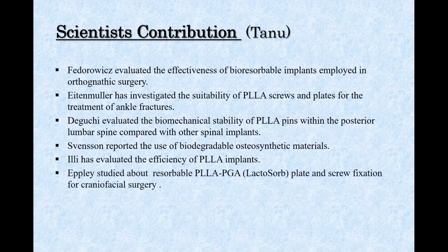In a study by Eppley and others, where resorbable poly-L-lactide polyglycolide plate and screw fixation for craniofacial surgery was applied in 1883 infants and young children, it was observed that device-related complications requiring reoperation occurred in less than 0.5% of the implanted patients, which is less frequent than reported for metallic bone fixation. Significant infectious complications occurred in 0.2%, device instability, primarily resulting from postoperative trauma, occurred in 0.3%, and self-limiting local foreign body reactions occurred in 0.7% of the treated patients. The overall reoperation rate attributable to identifiable device-related problems was 0.3%.